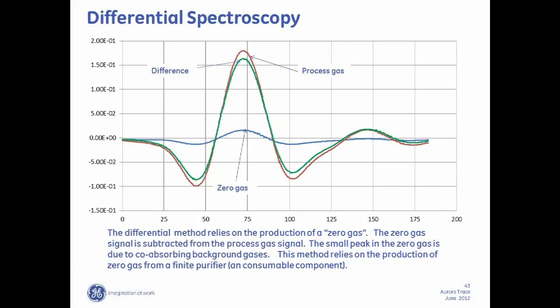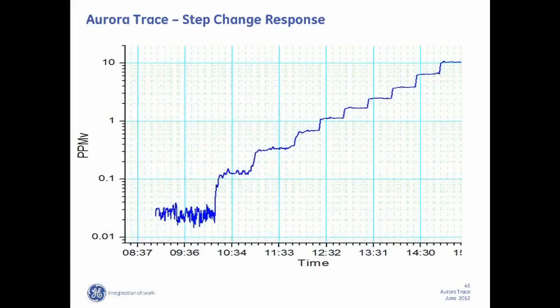And this is just data showing the response time of the Aurora-Trace as compared to a chilled mirror. Notice that it's on a logarithmic or exponential scale on the y-axis, but these were 3 different units that dry down. One of them was at a slightly faster flow rate, and the T90 here is less than 2 minutes. So again, very fast response times as compared to other technologies. And those are just step changes on the Aurora.